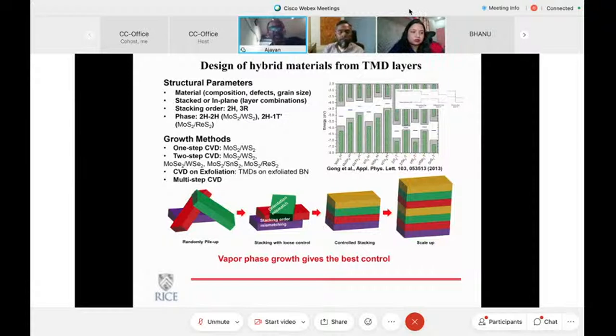And secondly, when you have a layer added on top of another layer, there is another stacking problem. Again, between two layers one can have different types of stacking: 2H stacking and 3R stacking. I don't want to go into details, but just to let you know that these end up as different stacking sequences. When you are actually putting these things together and building these multi-layer architectures, depending on how exactly the stacking occurs, you have different properties, because electronic interaction between the layers depends on stacking. And I will come back to that in a moment, which has led to some very interesting phenomena in recent times.